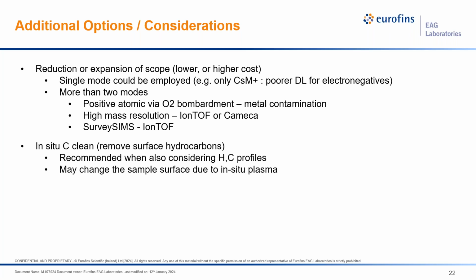We can also remove hydrocarbons in our tool. We basically have an in situ clean in the load lock that allows us to preferentially remove hydrocarbons prior to analysis. Though we have to consider that the sample surface might change a bit due to the in situ plasma being used in this process.